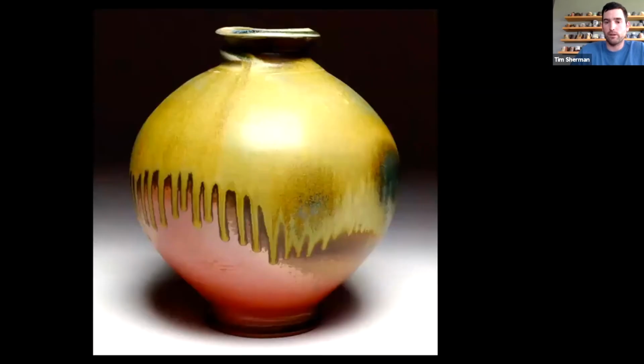That soft ash melt, I really love that. Over top of this is a Shino glaze with just natural ash on top of it. So a long, slow firing will give you these less long drips. I was getting pots that had drips that were 14 or 15 inches long, and they were going off the bottom of the pot. And that was from us firing too hot, too fast, and they couldn't hang on.